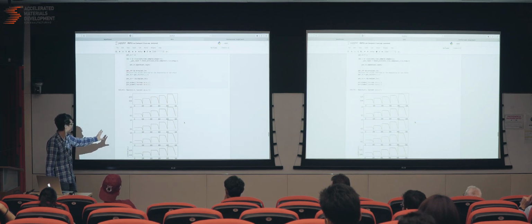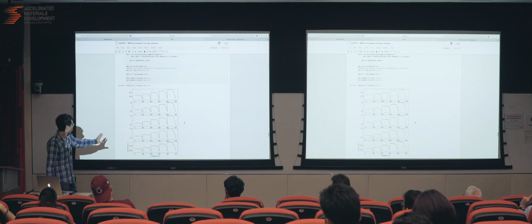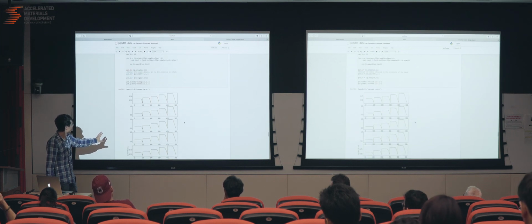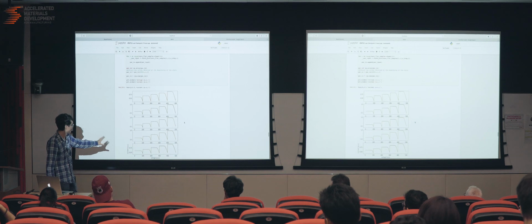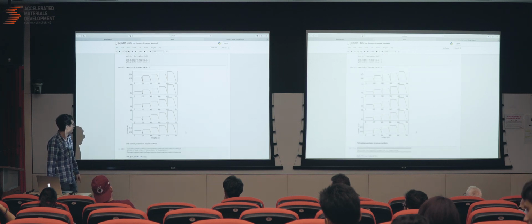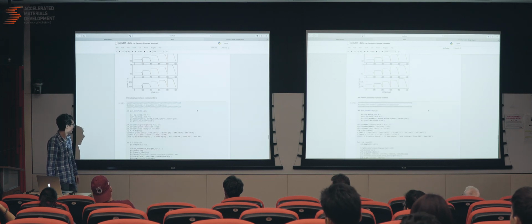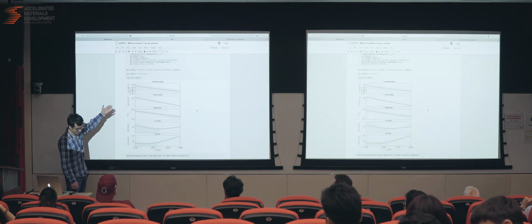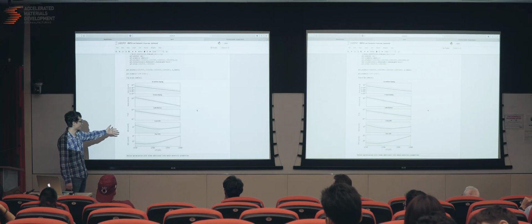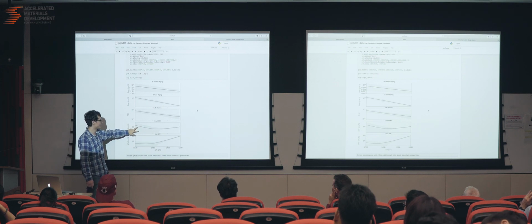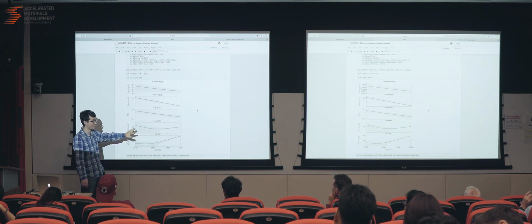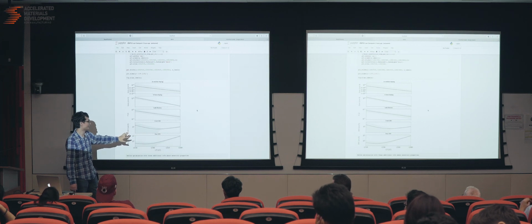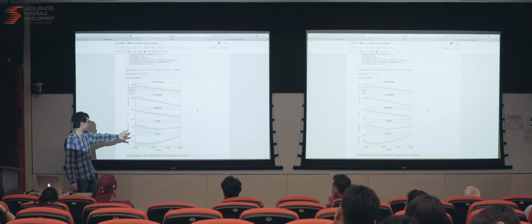So basically that's for the experimental ones. It recovers the experimental one except for this part, but that is because it has not been running for a long time. And we could even plot how the material parameters, in this case the doping levels, the lifetime and the interface recombination, change with the processing conditions. The dark area represents the uncertainty in your model, because this is a Bayesian framework. You are not having a single value, you're having a full distribution of that.